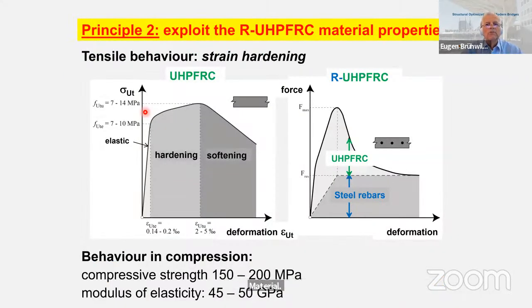Principle number 2 is, of course, we have to explore the material properties of this new material. In particular, the tensile properties, the elastic phase, the strain hardening phase, and also the significant softening phase of the tensile behavior here, the whole domain. We have a quite significant deformation behavior, or in other words, ductility. This resembles steel somehow, but of course the stress values are much lower. And that's why it is very interesting to combine UHPFRC with rebars. And from a mechanical viewpoint, this is rather simple. We add the response of steel rebars with the response of UHPFRC. It's a simple summation, the structural behavior.